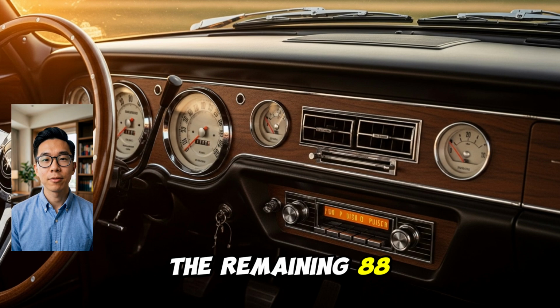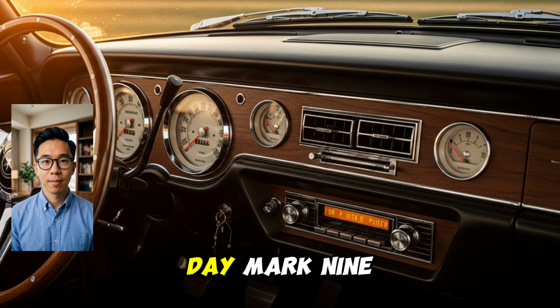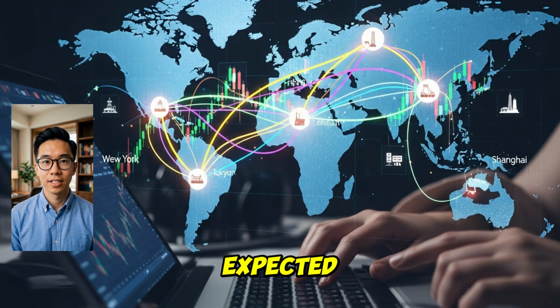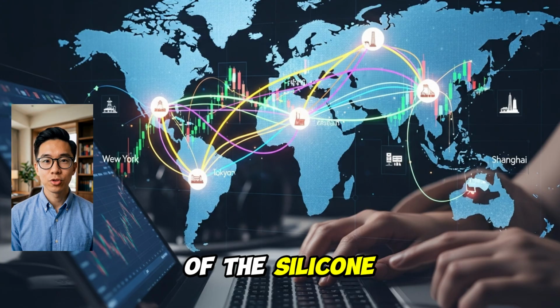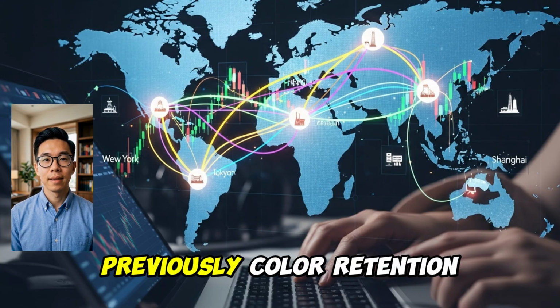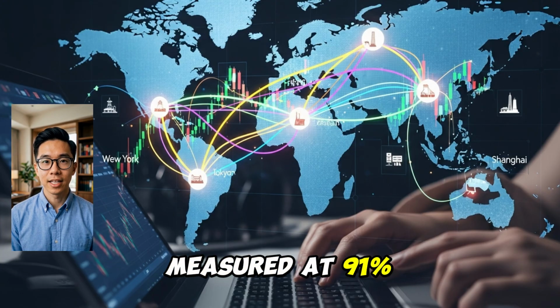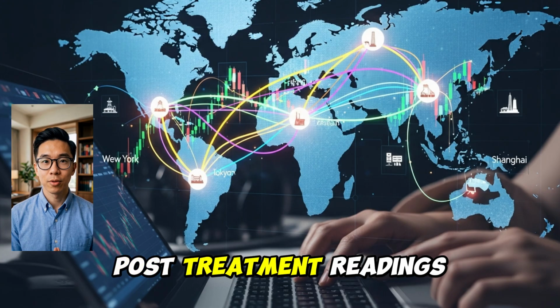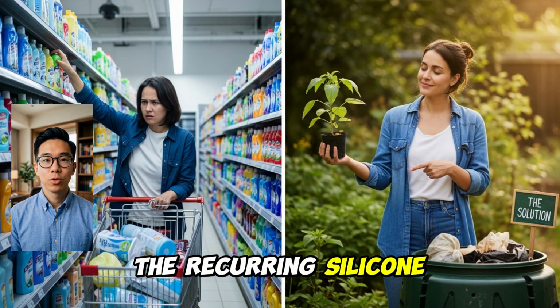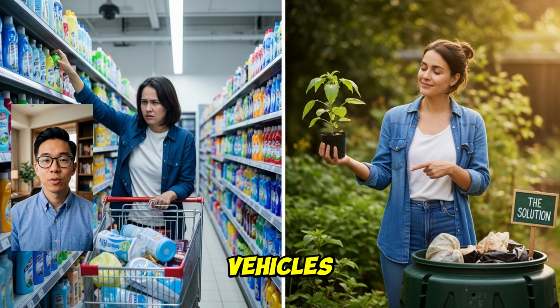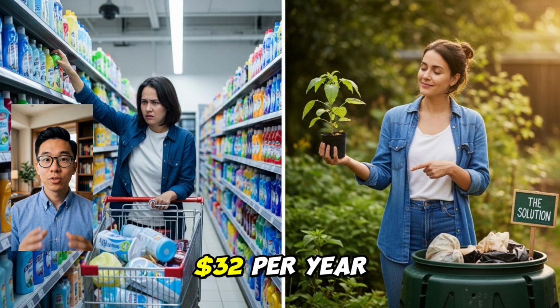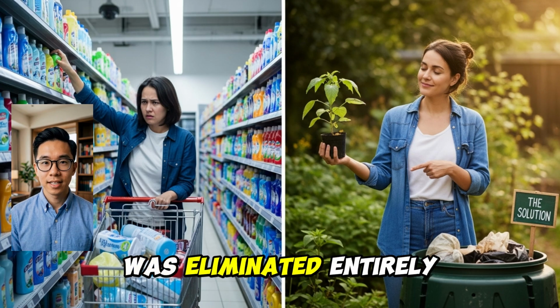The remaining 88 vehicles were reassessed at the 90-day mark, 9 months beyond the expected effective window of the silicone dressing the facility had used previously. Color retention measured at 91% of immediate post-treatment readings. The recurring silicone treatment budget for those 88 vehicles, previously $132 per year, was eliminated entirely.